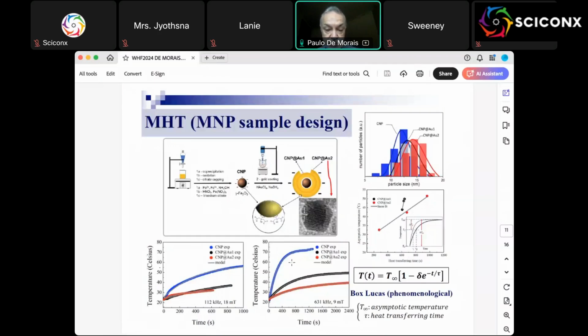However, if you take the same samples and change the AC frequency from 112 to 631 kilohertz and lower the amplitude of the AC field by half, from 18 millitesla to 9 millitesla, and then check the response, the uncoated maghemite nanoparticles go higher in asymptotic temperature, higher than 70 C, which is not desirable. However, the thinner gold coating on top of the same maghemite nanoparticles goes exactly in the range which is desirable to perform magnetic hyperthermia in terms of thermal sensitization.